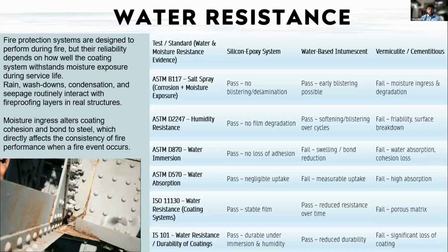Then ISO 11130, water resistance. Silicone epoxy passes the test. Water-based also passed this test, but vermiculite fails this test due to its porous matrix. IS 101, water resistance or durability of the coating. Silicone epoxy passes and is durable under immersion and humidity. Water-based passes but with reduced durability, and vermiculite fails with a significant loss of coating.